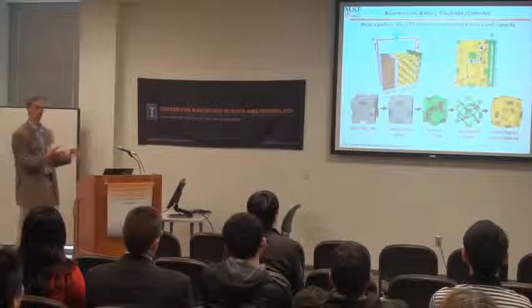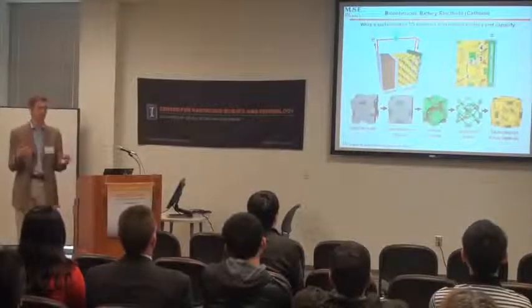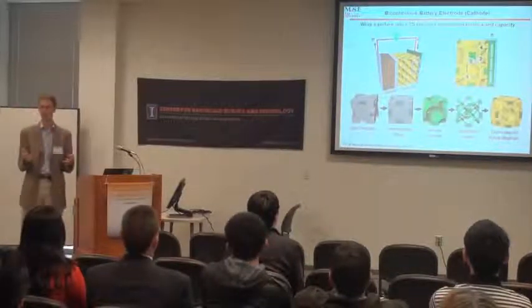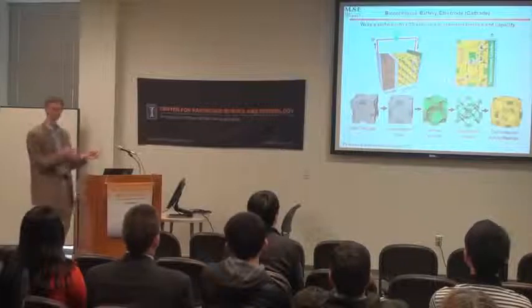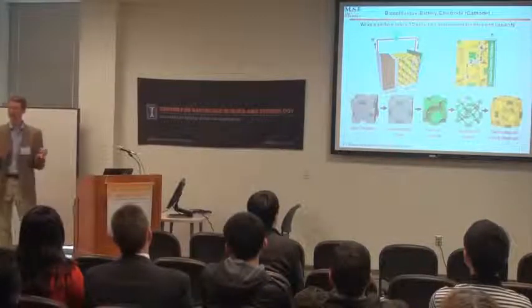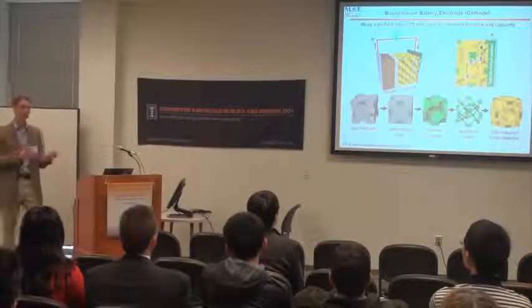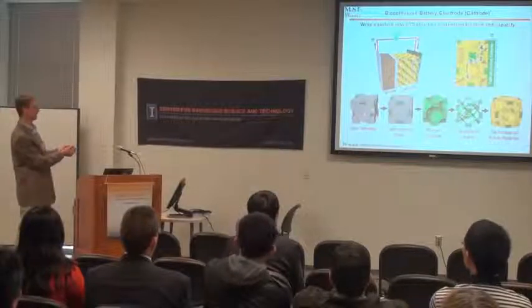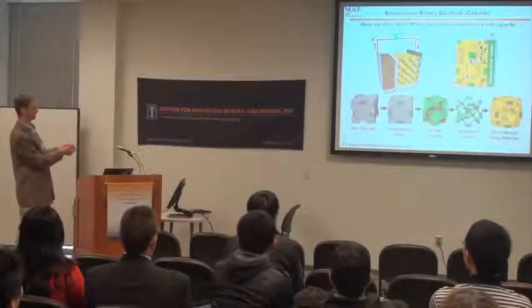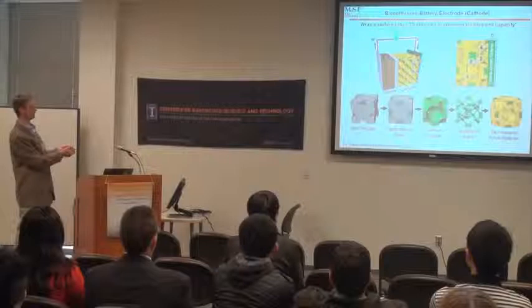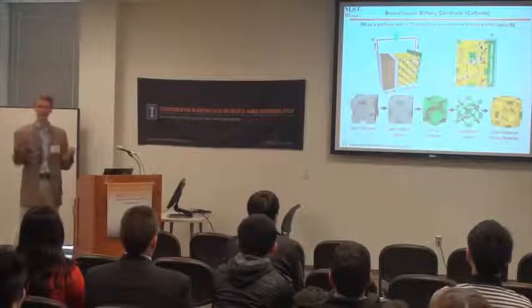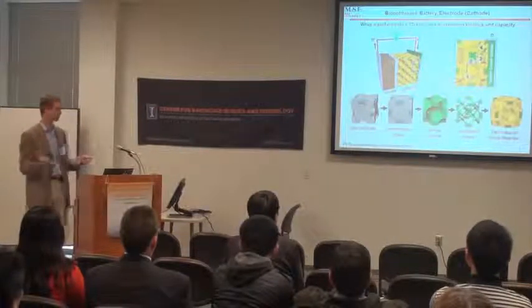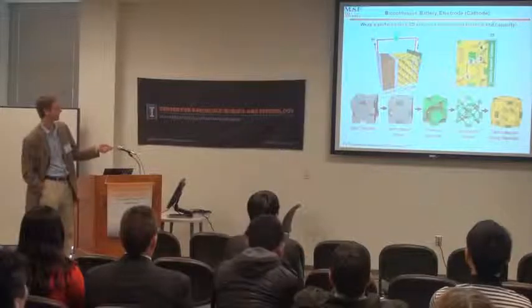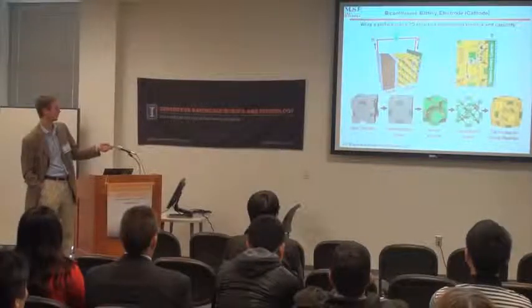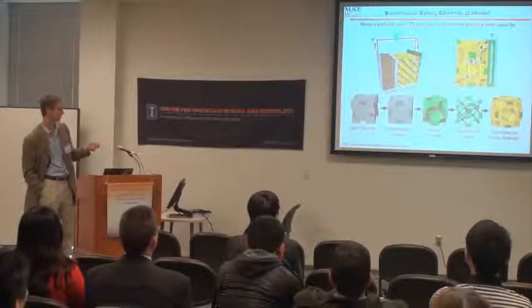And so starting with these colloidal approaches, and the colloidal crystals we liked, again, because they can be self-assembled, and in fact, for a battery, unlike for the photonics, a few defects don't matter. So in photonics, we would worry about defects all the time. Here in batteries, you don't need to worry about that at all. You get a small decrease in energy, but not much. And so you can self-assemble this structure, and then electroplate material into that. So now these are relatively scalable approaches. But the trick is when you remove the particles, you end up with very, very small openings.